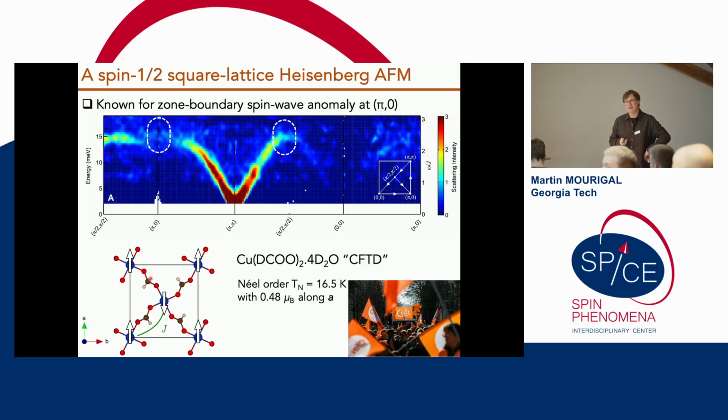So, these two-magnon attraction peaks that develop, could I think of that as a bound state of two magnons? It's not a bound state in the sense that it lives inside the continuum. The bound state usually goes below the continuum. Here it's some quasi-bound state, or I don't know what you want to call it. It's some enhanced density of states for two magnons. A resonance might be a way to talk about it. Yeah, that's good.